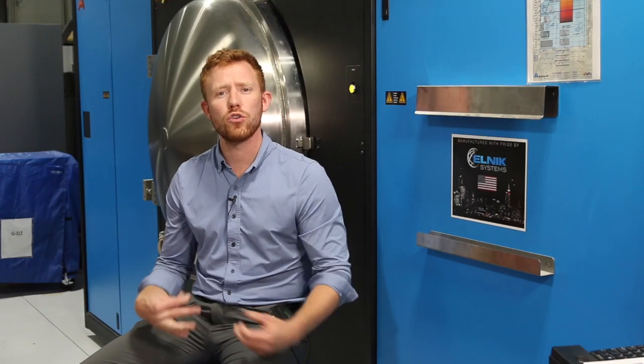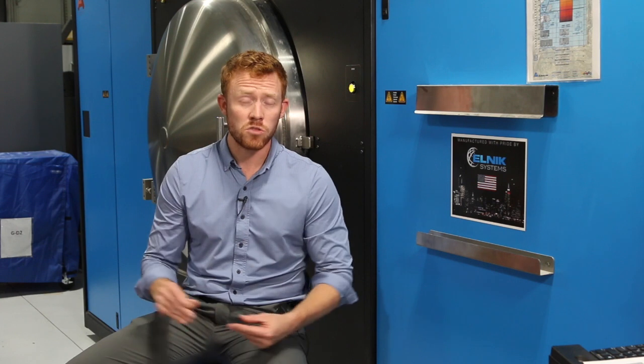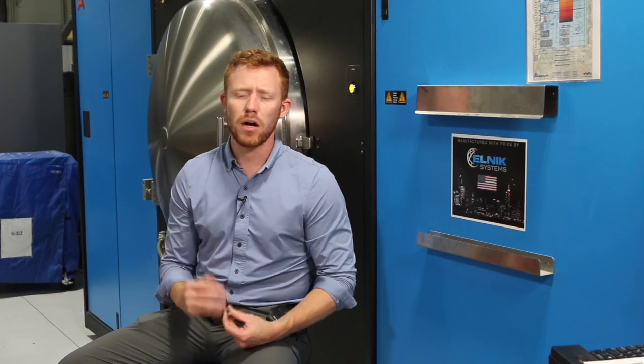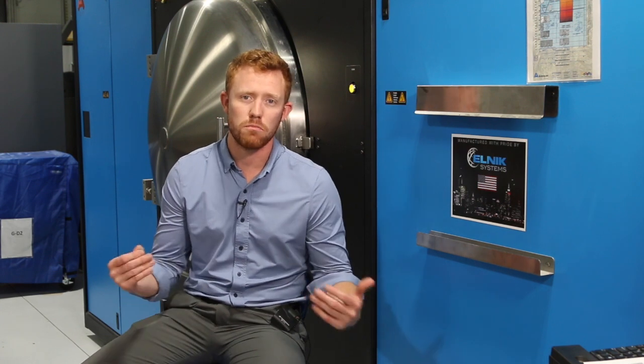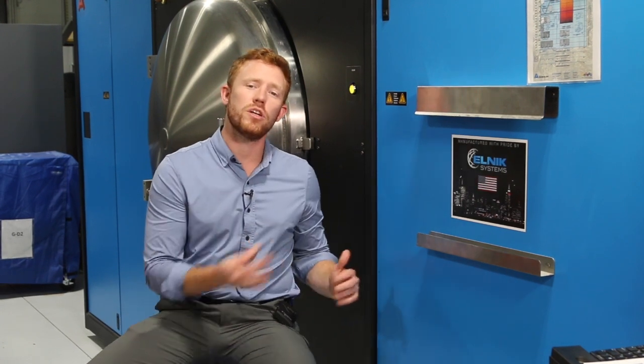So at Azoth, what we're doing behind the scenes is we're scaling your part up for that shrinkage factor. We're considering a cycle based on your material, the cross section, the dimensions that you want, and we're custom tuning a specific cycle. And when we talk about industry known standards and operating to standards from the metal injection molding industry, it's what happens in your furnace that really enables you to get those mechanical properties.